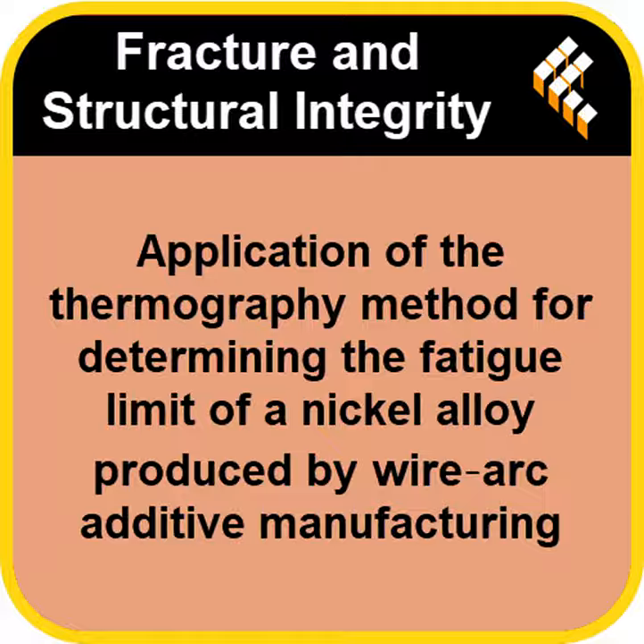And here's the problem, the core dilemma. Traditional testing is just painfully slow. To find the fatigue limit, that's the magic number, right? The stress level it can handle forever. That's the one. And to find it, you have to run what's called an SN curve method. Yeah. You're testing multiple samples up to 10 million cycles. 10 million? That's a huge number. It is. That can take months, sometimes half a year. It burns through equipment, material, time. If you're trying to innovate quickly, that wait is just an innovation killer.